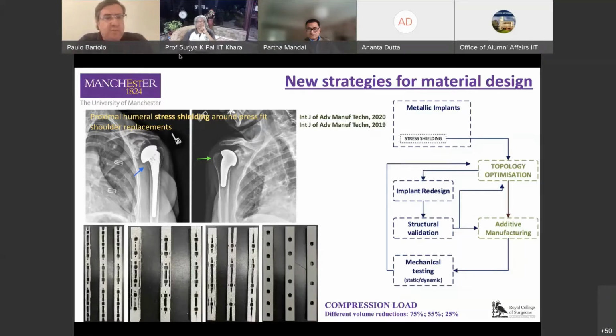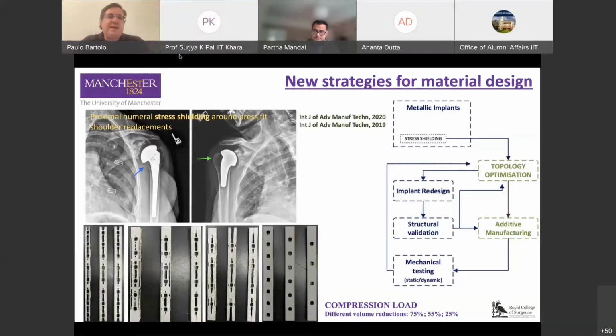We are exploring this for multiple areas. An example that I decided to bring today is related to medical applications. The case that I'm bringing here is related to the redesign of bone fixation plates. These plates are made in titanium alloys or stainless steel, sometimes chromium cobalt. The main issue is that they present very high mechanical properties compared to the bone. As a consequence, we have a phenomenon called stress shielding, and as a consequence of stress shielding, there is some bone loss in the vicinity of the plates.